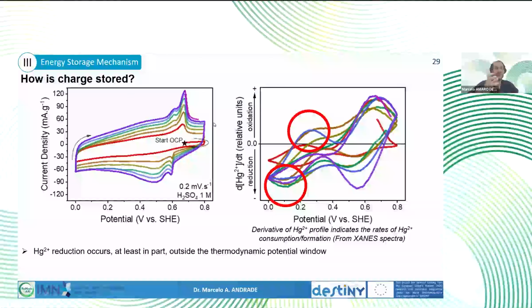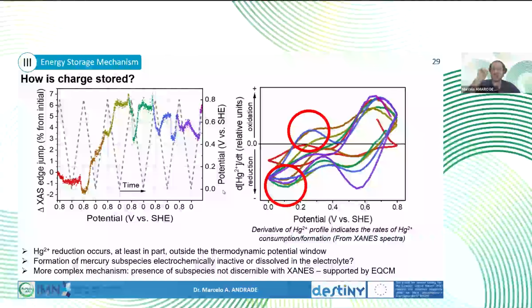But there's something chemically happening there that is masked on the cyclic voltammetry, and it is out of the thermodynamic potential window for mercury. So we attributed that to the formation of mercury that was either electrochemically inactive or that could be dissolved in the electrolyte, because that was irreversible. And probably a more complex mechanism for mercury, which is a very tricky cation that could not be discernible by XANES.